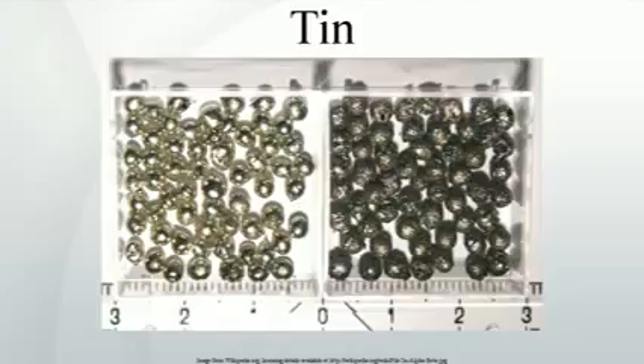In cold conditions, β-tin tends to transform spontaneously into α-tin, a phenomenon known as tin pest. Although the α-β transformation temperature is nominally 13.2 °C, 55.8 °F, impurities, for example Al, Zn, etc., lower the transition temperature well below 0 °C, 32 °F, and upon addition of Sb or Bi the transformation may not occur at all, increasing the durability of the tin.